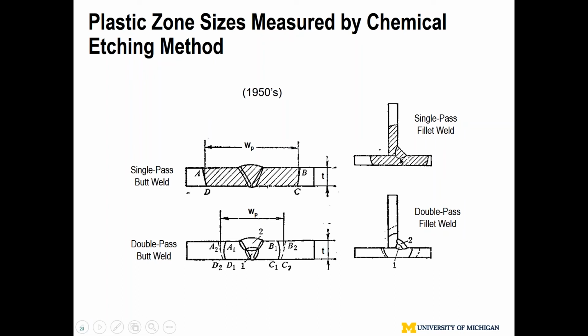In the meantime, why do we want to reduce weld size? Here the weld size increases from 5 millimeter to 7 millimeter, for shipbuilding applications. You can see the plastic zone width WP gets increased. Essentially, the total area is doubled by increasing the fillet weld leg size from 5 millimeter to 7 millimeter. This concept was used in the 1950s by the Russians, but a lot of people don't do that anymore. They did some classical work in the 50s, so I managed to find the original reference.